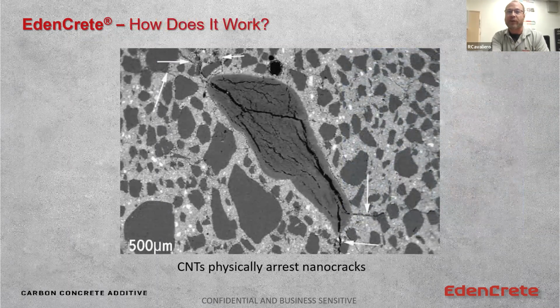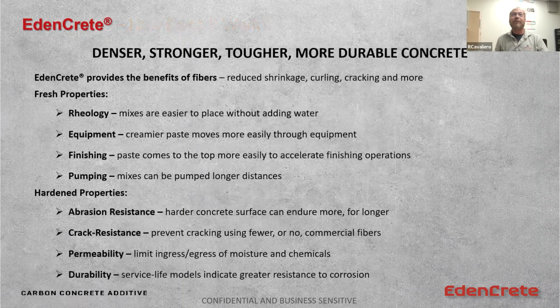So essentially here on a scanning electron microscope image that's been lapped, what we're doing at a nano scale is we're physically arresting those cracks, right? The carbon nanotubes physically bridge those cracks, but there's so many of them in so many different orientations that they flood the cement paste matrix and they provide benefits in a multitude of ways that we honestly still learn more about. We call them happy accidents.